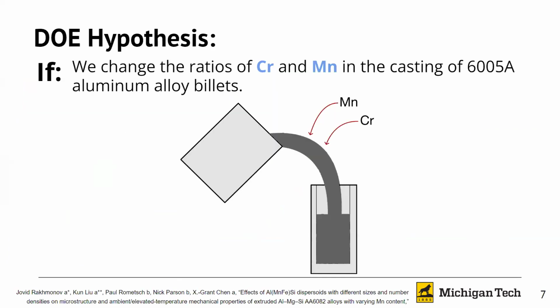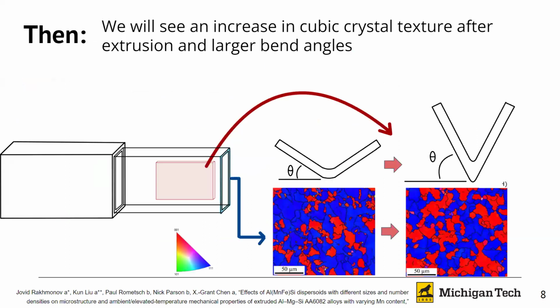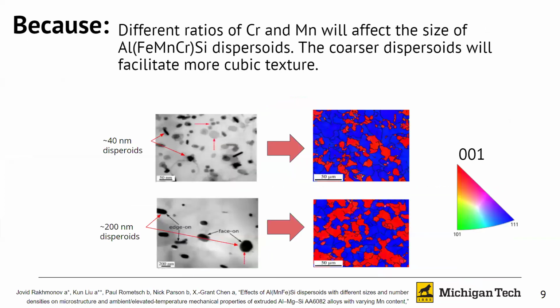We hypothesized that if we change the ratio of chromium and manganese in the casting of 6005A aluminum, then we will see an increase in the cubic crystal texture after extrusion and larger bend angles. This is because different ratios of chromium and manganese will affect the size of aluminum, iron, manganese, chromium, silicon dispersoids. The coarser the dispersoid, the more cubic texture it will facilitate.